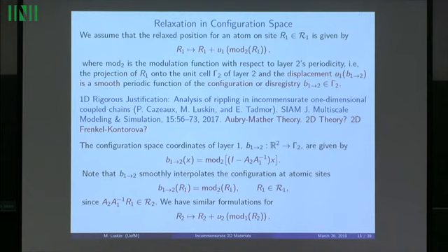But what we want is to smoothly interpolate this function, because when we have, let's say, a small angle, or the lattice constants are varying not too greatly, then as we move from atom to atom, the disregistry is very slowly varying.